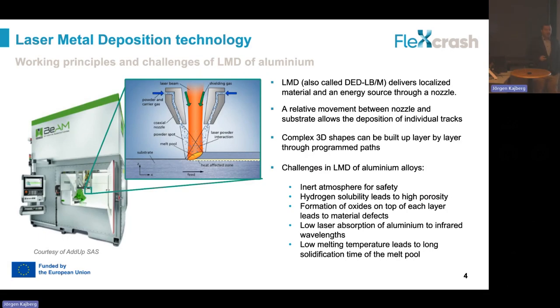By pre-programming the movement of the nozzle above the substrate, we can create complex 3D shapes. As the previous speakers already introduced, in this work we are working with aluminum alloys, and this presents a significant challenge when 3D printing aluminum, especially with lasers. Mainly for two reasons. One is the high reactivity of aluminum, especially when in molten state, with hydrogen and oxygen from the atmosphere. And the other one is the laser interaction with the material.